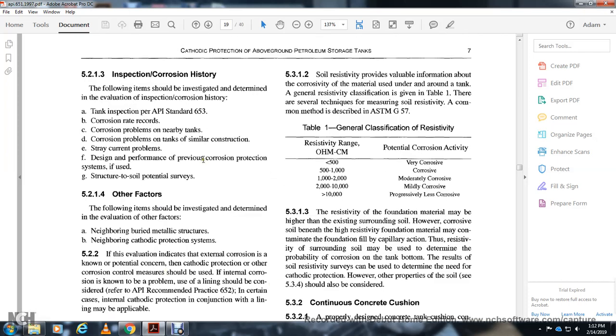Alright, 5.3.1.2, soil resistivity provides valuable information on the corrosivity of the material under and around the tank. There are several techniques for measuring soil resistivity, including the method described in ASTM G57. Table 1 shows the general classification of resistivity: less than 500, 500 to 1,000, 1,000 to 2,000, 2,000 to 10,000, and over 10,000 ohm-cm, from very corrosive, moderately corrosive, mildly corrosive, to progressively less corrosive.